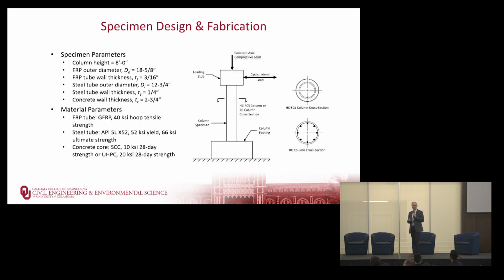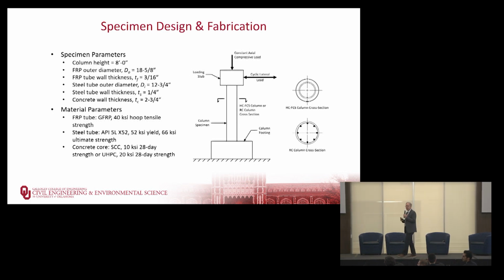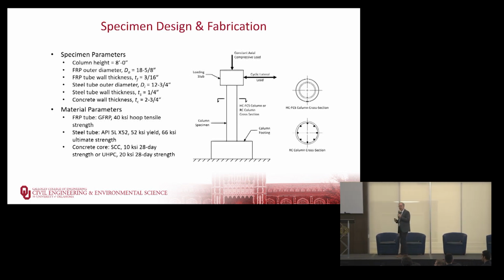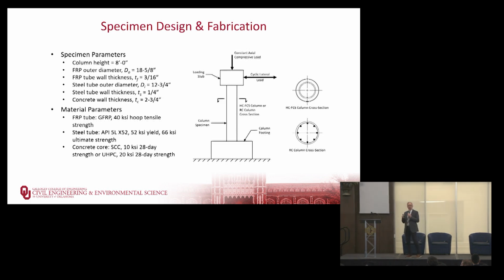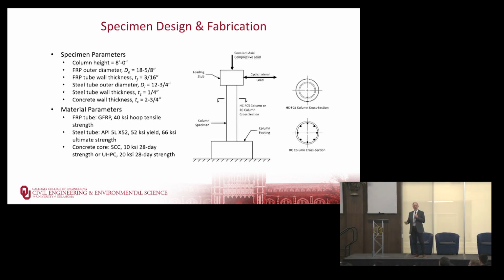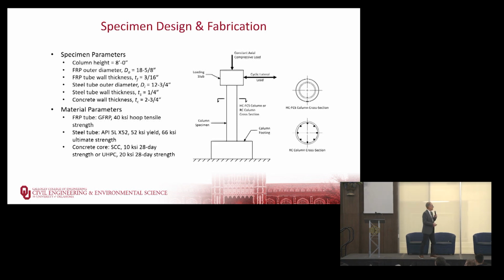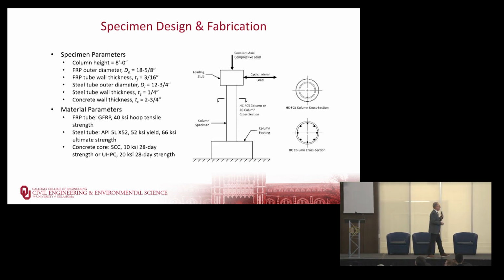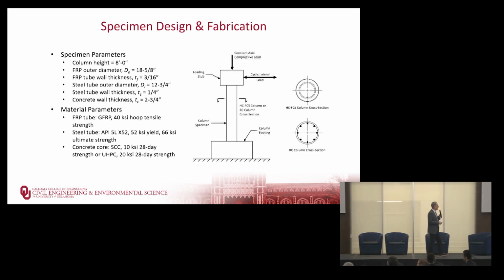We use high strength SCC, right? We want concrete that can flow very well to get into that 2 3/4 inch space. And again, if you have a concrete that flows very well, there's less labor involved. You just pour it in, you're done. You don't have to vibrate it. You don't have to do anything. So we use high strength SCC with a compressive strength at 28 days of 10 KSI.